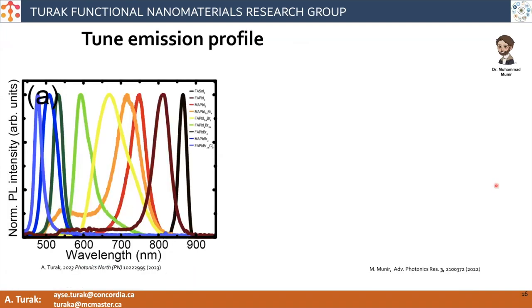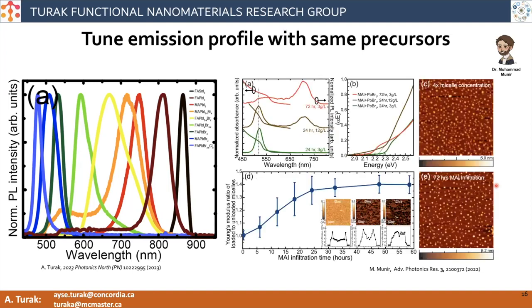And this allows us, as many people do, to tune the emission profile. The typical way is to just change the precursors, which we also do. You can get the full spectrum of emission from nanoparticles with a lot of intensity, relatively high quantum yields above 50%, from blue almost into the infrared. But the uniqueness of using the dye block copolymer is that, using the same precursor mixtures without changing the precursors, we can also change this emission.